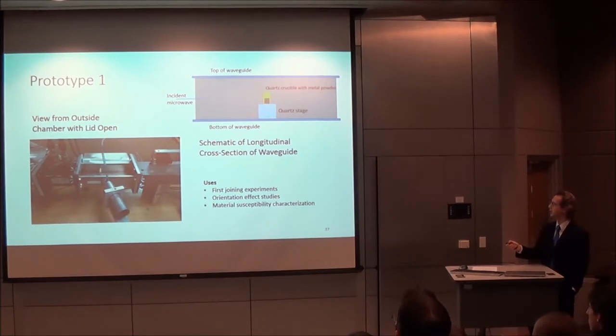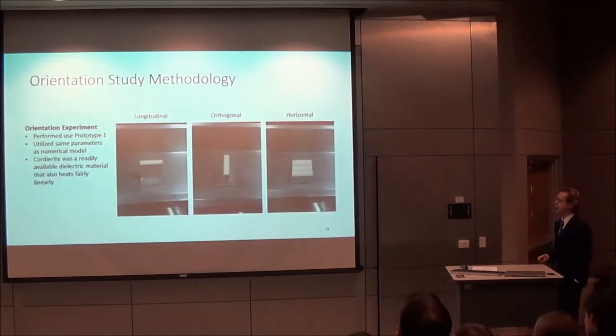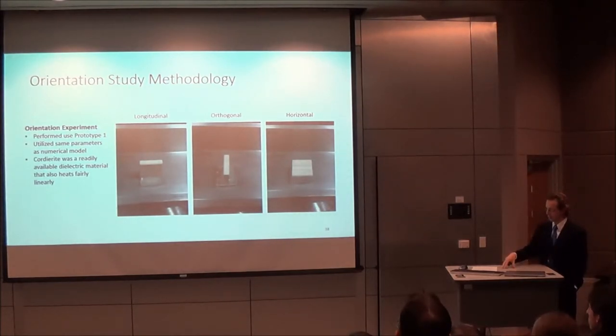Here's a diagram of another experimental configuration where a metal powder is placed in this quartz crucible and heated for a particular time at a certain power in the microwave, on the quartz stage. And so the orientation study was done in this manner. A dielectric brick was placed in three different orientations, as illustrated with the numerical model. It utilized the same parameters as the numerical model in terms of power, back wall position, and time, and Cordierite was chosen just as a readily available dielectric material.